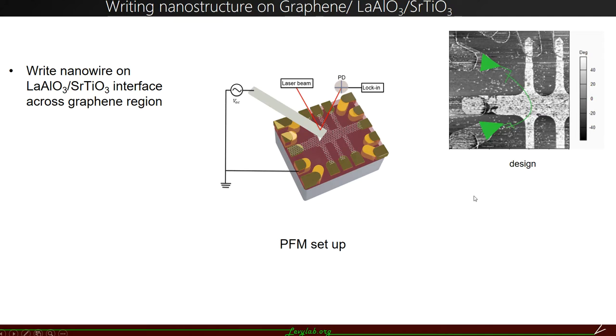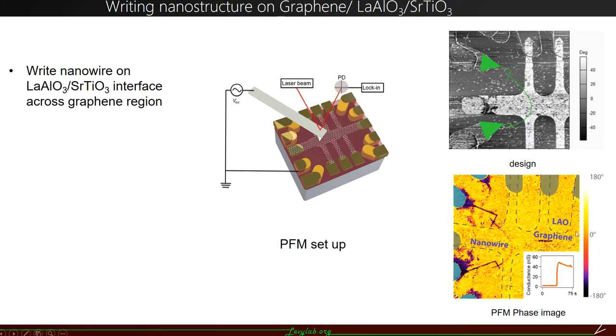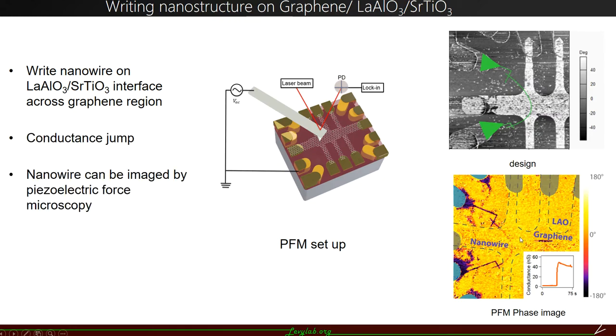So here comes the question: can we still write nanostructures with graphene on top of LAO-STO? The answer is yes. So here we designed a pattern with two triangular shaped conducting regions and one nanowire that goes across the graphene. After the writing, we see the conductance jump between these two electrodes, and from a PFM image, we can see that the wire looks exactly the same as we designed.